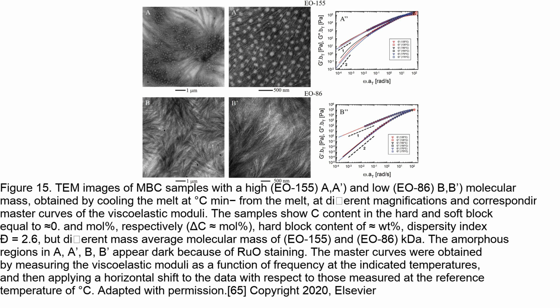The difference in solid-state morphology can be attributed to the higher length of the soft blocks for the EO86 sample, and the presence of additional PE lamellae that cross the matrix rich in soft blocks and connect neighboring domains rich in hard blocks, forming a web-like structure for the EO155 sample.